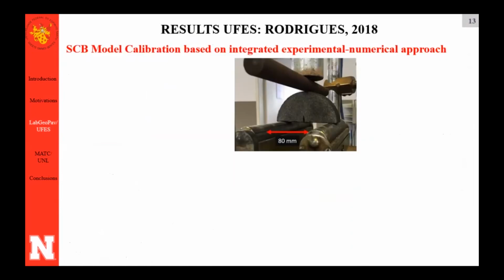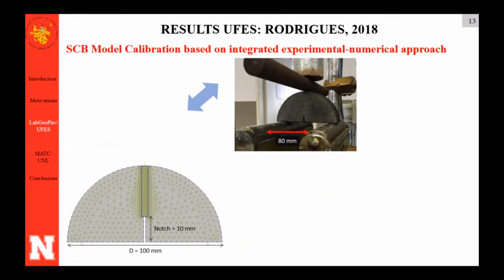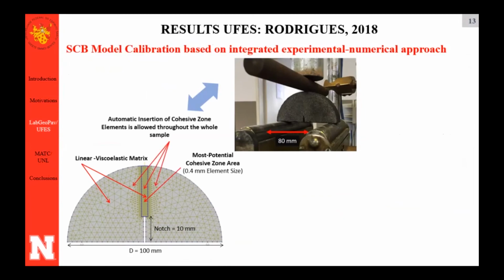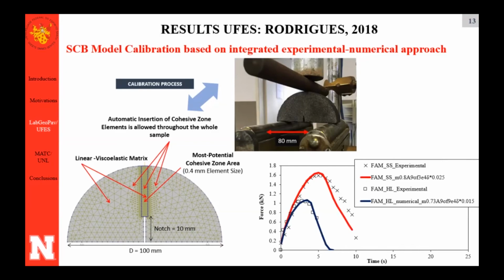So she did the DSR test, got the linear viscoelastic properties. Then she did the SCB test, where she allowed cohesive zones to develop throughout the sample. And she played with the parameters until she got a nice correlation between experimental and numerical results. That's what we call a calibration process. And from that, you can see here experimental results in black and numerical results as the colored lines. You can see here comparing the fine aggregate matrix with slag and the fine aggregate matrix with hydrated lime.